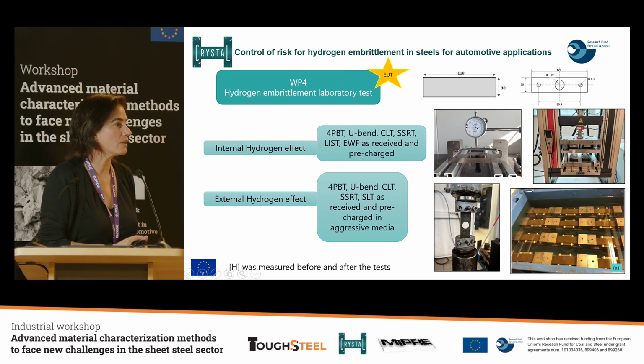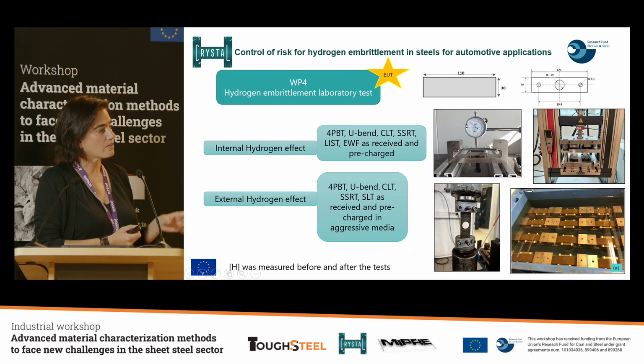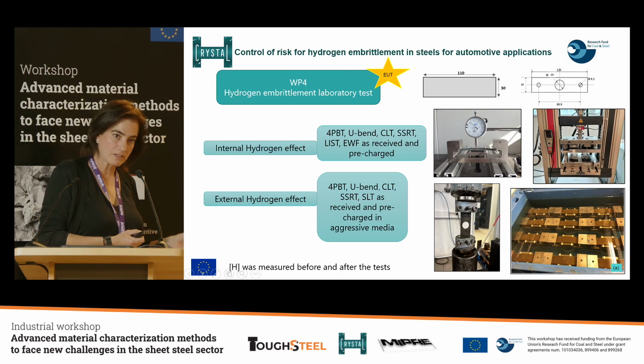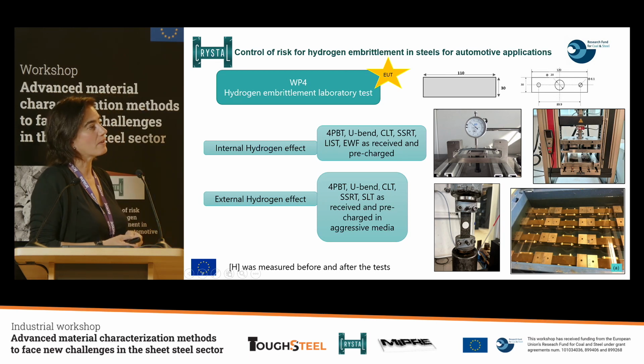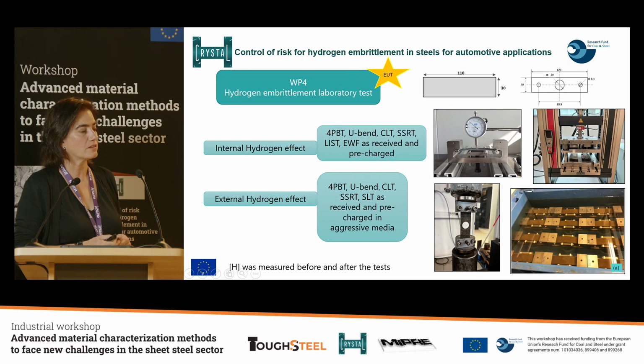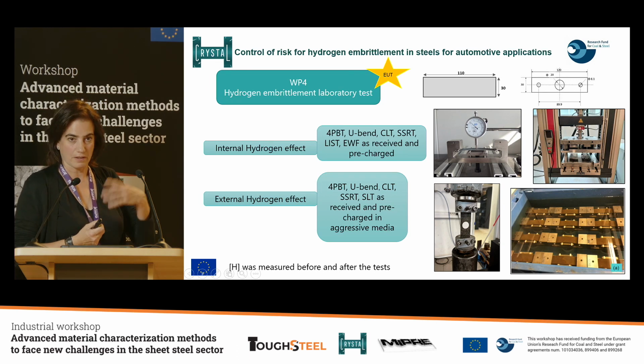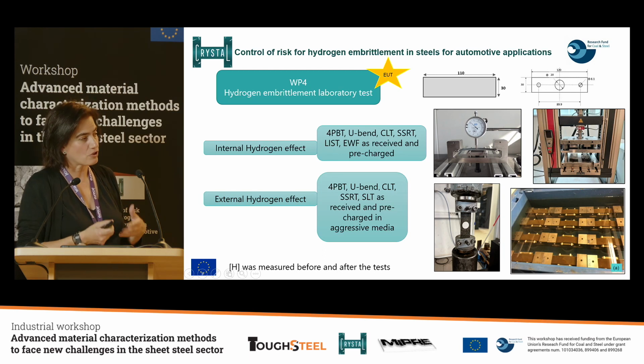Also, I would like to add that in all the cases, we measured the hydrogen content before the test and after the test. Because in some cases, for example, in the constant load test, the duration of the test is quite long. So we wanted to be sure that we don't have hydrogen uptake during the test. I mean, the gaseous uptake of hydrogen during the test.